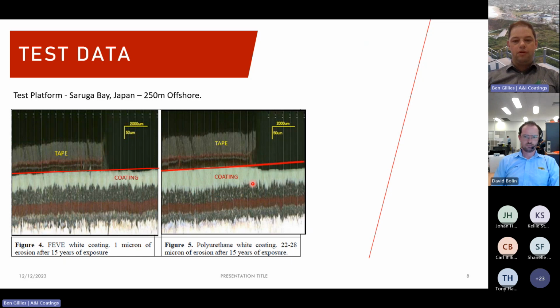This slide here shows what we call film erosion. Over time, as a coating is subjected to harsh weather patterns, it starts to lose its film build. And that manifests itself in the appearance of chalking, loss of gloss. It looks old, it looks tired. We've all seen those structures. What this slide shows on the left-hand side is a cross-section of a fluoropolymer coated sample. So you've got a primer, an intermediate coat, and a top coat. And up the top here, they've just called it tape. That is basically a cover for half a panel, so that when you remove the panels from the test structure, you can take off the tape and you can see with and without exposure the difference.